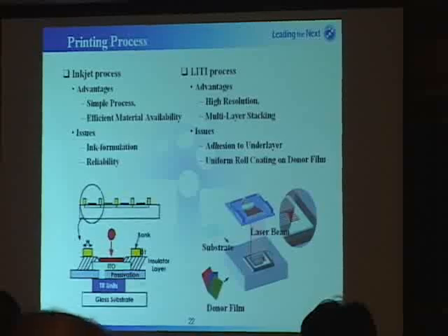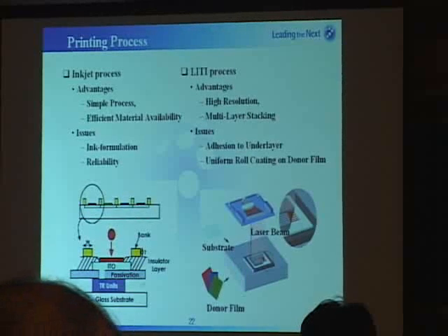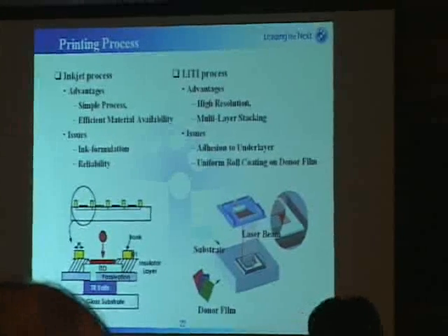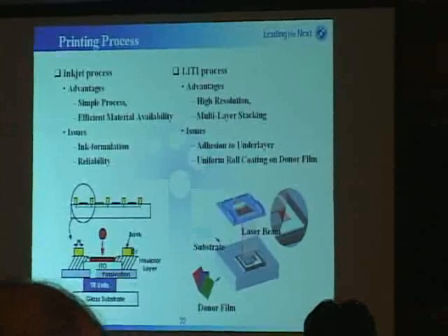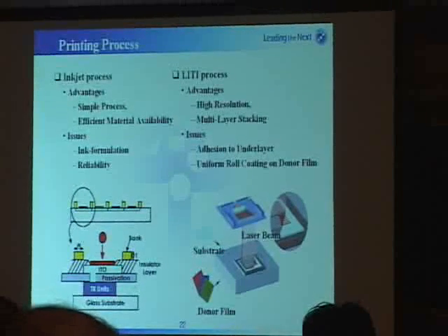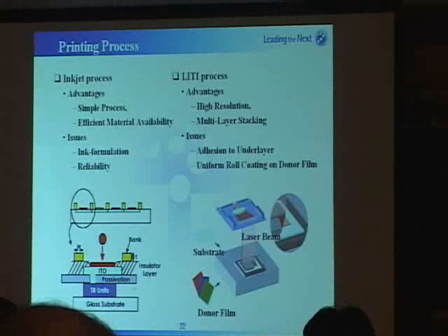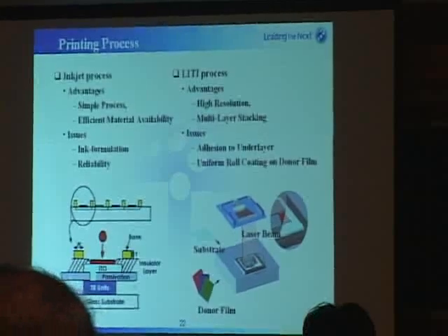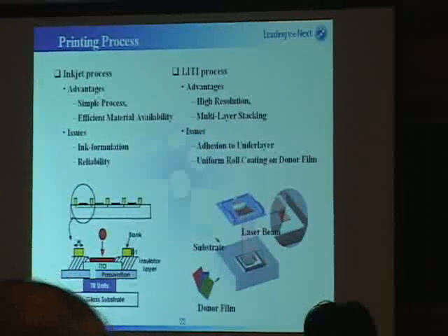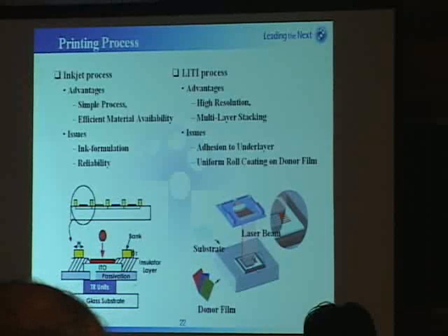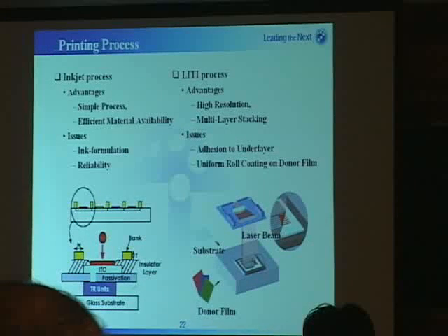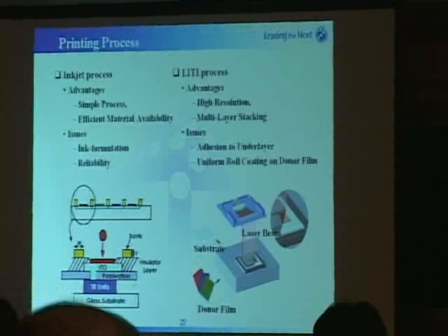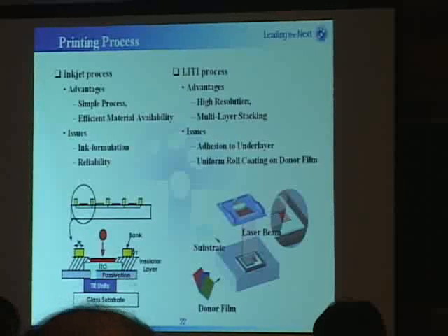LITI process: laser-induced thermal imaging. Its advantage is high resolution. Patterns of only a few microns are possible to make. Multi-layer stacking is also possible. It's also a good advantage. As an issue, adhesion to the underlayer and uniform roll coating of donor films are not so easy because the donor film is so thin.